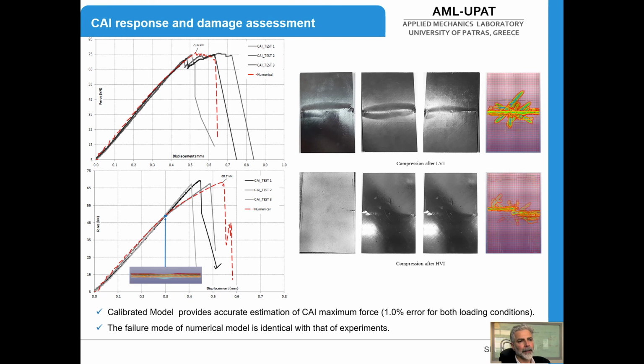Following the identification of delamination area and the comparison between the experimental and the numerical results of the delaminated area, now we consider the compression after impact test. At the top you may see the results in the case of low velocity impact, while at the bottom you may see the results of compression after impact in the case of samples that have been exposed to high velocity impact. You may see in both cases, low and high velocity impact, there is a very good capture of the maximum force at which the impacted plate fails.